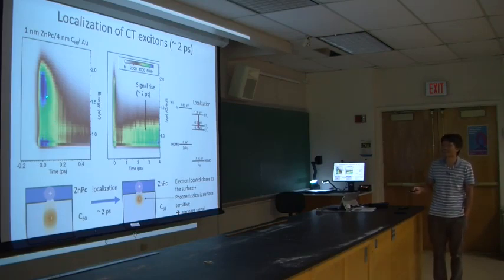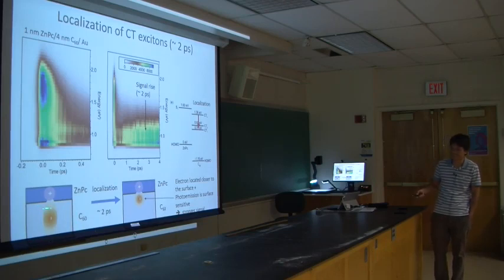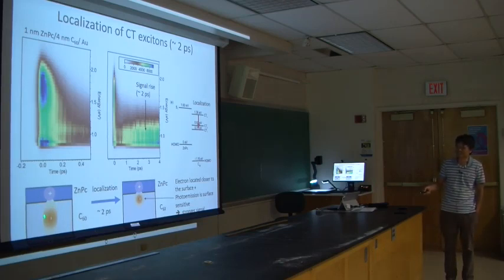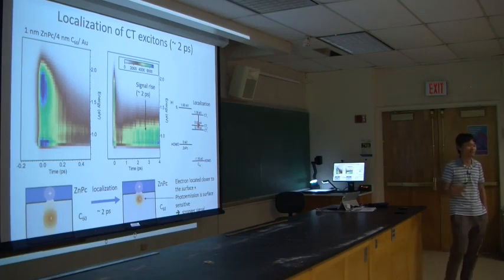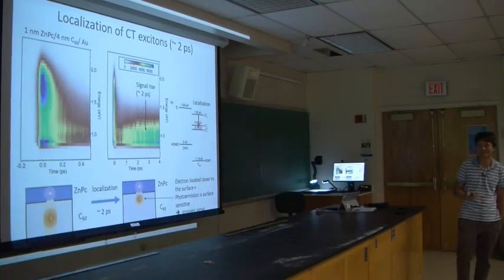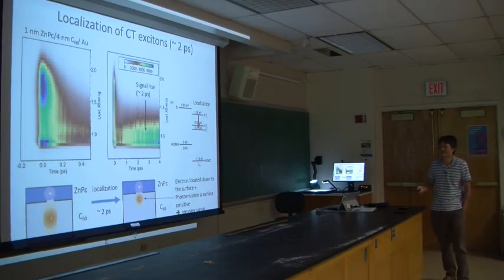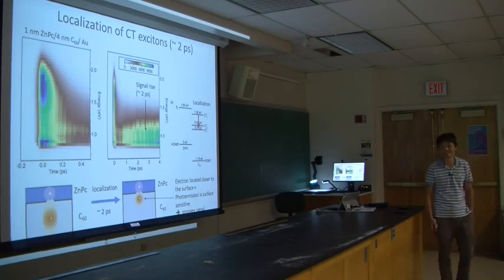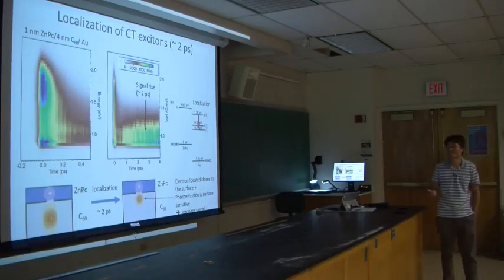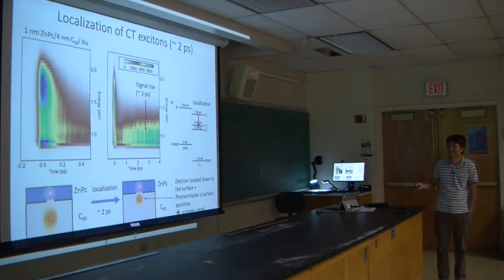So what we think is happening is initially we populate this so-called delocalized CT state, right? They are delocalized in the sense that the electron is, on average, farther away from the interface. Because now our probe is photoemission, right? Photoemission is a very surface sensitive technique. So when your electron is located farther away from the interface, your signal gets really weak, right? That's why apparently this signal disappears. But if we look at the spectrum more carefully, we can actually see a peak around here, which fills this time gap. So you actually populate this delocalized state, which has the electronic wave function farther away from the interface.